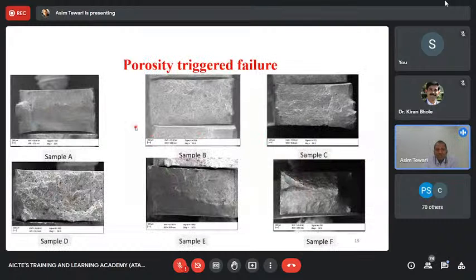If you look at the fracture surface, once the sample fails, you can start seeing the evidence of porosity on it. If the fraction of porosity on the fracture surface is more than the fraction of porosity in the cross section of any plane, then it means your fracture surface is following porosities, and thus porosity is getting bridged as the fracture surface forms. That is what we see in almost all these samples: porosity plays a dominant role in leading to fracture. So one of the biggest challenges in additive manufacturing becomes porosity, and porosity, of course, triggers fracture.